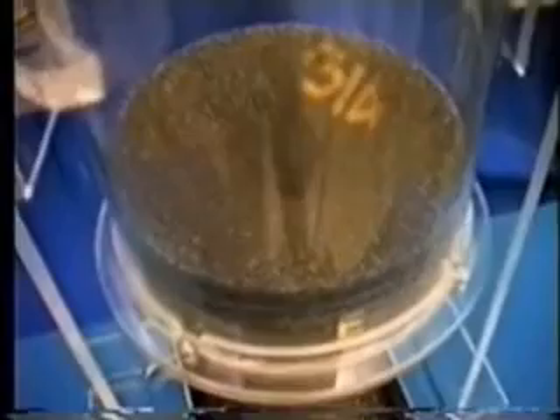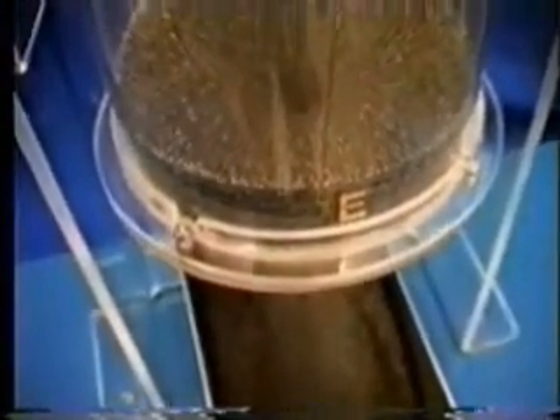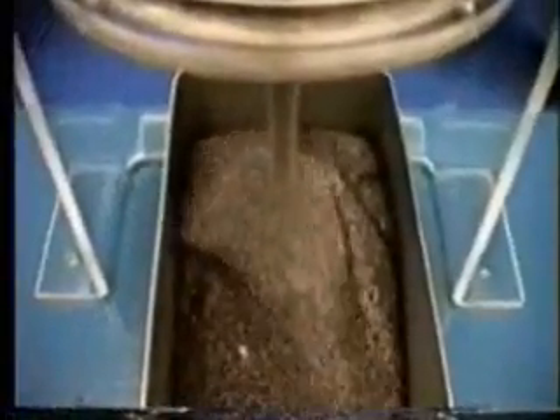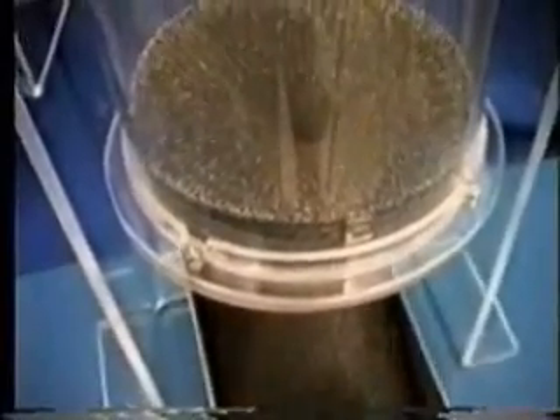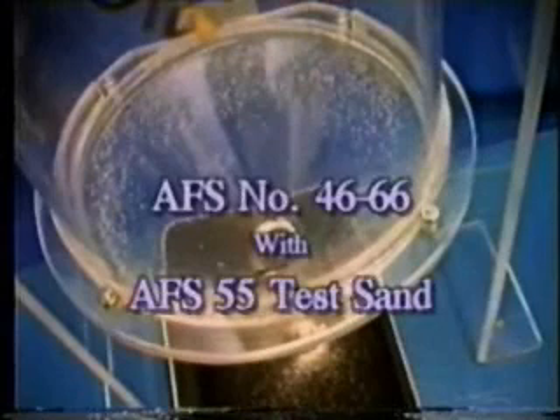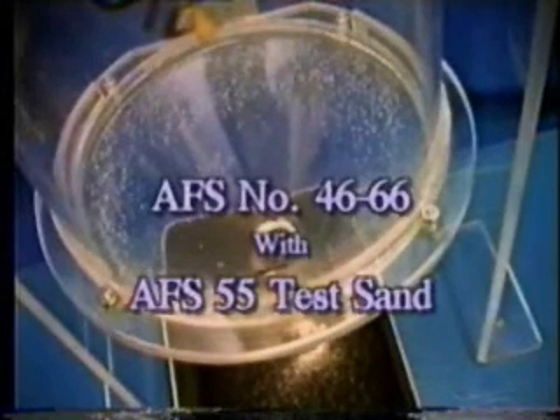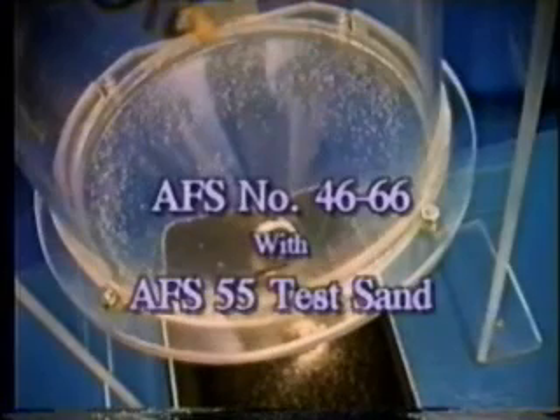This phenomenon, known as rat holing, can be seen as the center dome of sand collapses into the center of the bin as it empties. After the fine sand is gone, coarse sand falls into the funnel and discharges rapidly. This results in a wide variation in the screen distribution of the sand exiting the bin. Variations from an AFS number of 46 to 66 were experienced with the 55 AFS test sand.